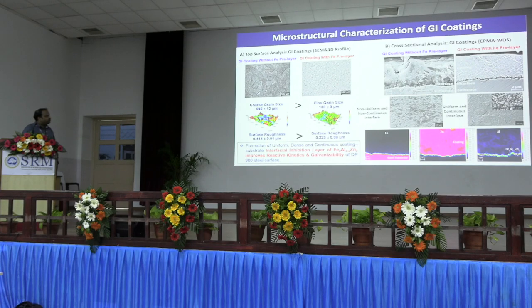And when we carried out the cross-sectional analysis, we confirmed the formation of the inhibition layer, which is the important key factor for the good adhesive strength of the galvanizing coating on the steel surface, very important during further forming operations for structural and automotive applications. And the formation of this very uniform dense inhibition layer of Fe2Al5 is an indication of the suppression of surface selective oxidation and segregation of the alloying elements on the DP980 steel, getting the uniform inhibition layer and suppressing the main issue of the formation of uncoated spots during the galvanizing process.